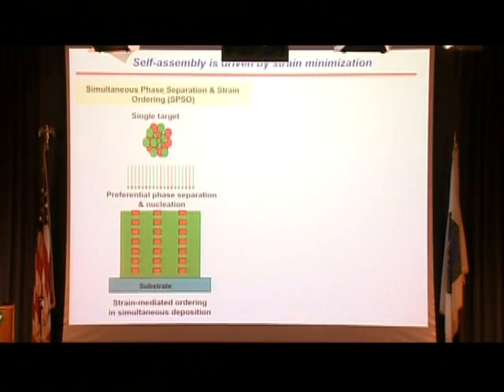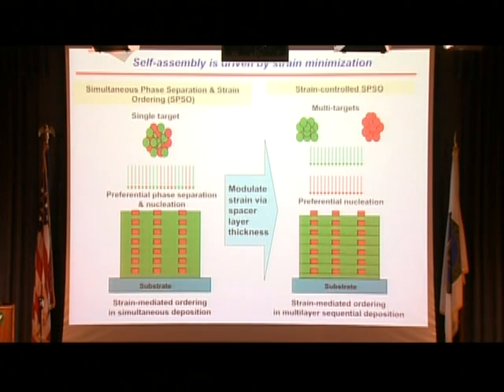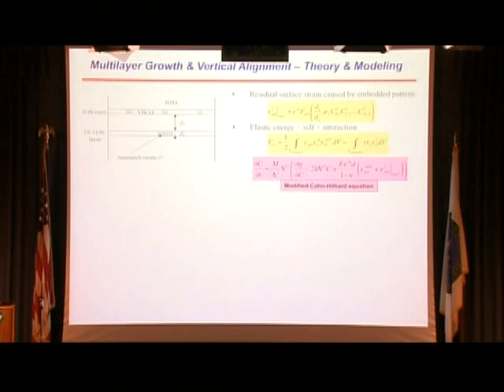In fact, we did a lot of this work, so let me actually go back a little. We know that this occurs by strain minimization. But to show that it occurs by strain minimization and that these nanodots are aligning up within the material by a self-assembly process to minimize the strain energy, we can do an experiment by separating the strain here by changing the distance between 2 nanodots. And we can do that by doing a different kind of deposition than the way we were making these materials, by depositing the red and the green atoms, one being the superconductor, one not being the superconductor, together. So when we do that, we can actually model this too, using theory and modeling.